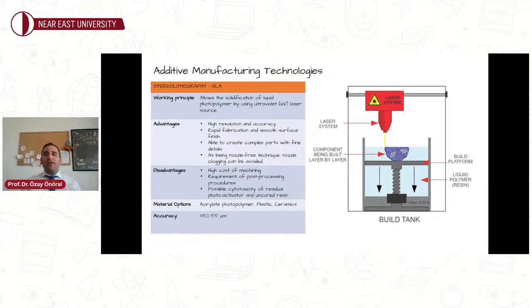SLA is most probably the first commercially available 3D printing technology. This rapid manufacturing method involves photo-induced free radical polymerization to create layered structures by using highly cross-linked polymers. The exposure of the monomer activates the polymerization reaction, which stops locally due to the solidification and limited movement of the free monomers.